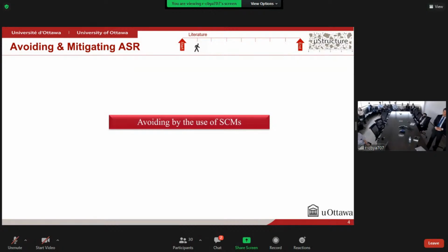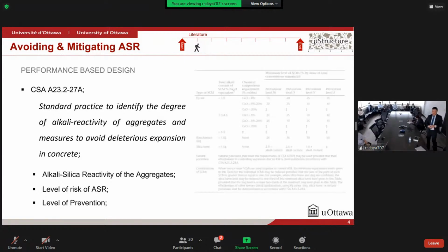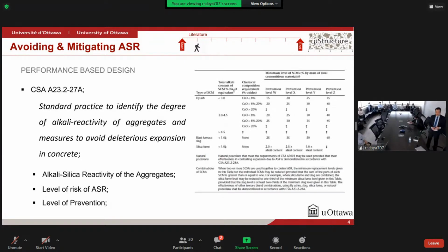Another way is through the use of supplementary cementing materials, which are byproducts from different industries. These materials can be used in combination with cement to enhance the hardened properties of the concrete. For example, here in Canada, we have performance-based design standards that give us engineers good practice to identify the degree of alkali reactivity of aggregates and measures to avoid deleterious expansion in concrete. For that, it's necessary to know the reactivity of the aggregates and the level of risk of ASR development. With that information, we can then select the best level of prevention, which is basically this table here that gives us the minimum amount of cement replacement by the most common types of SCMs used in Canada.